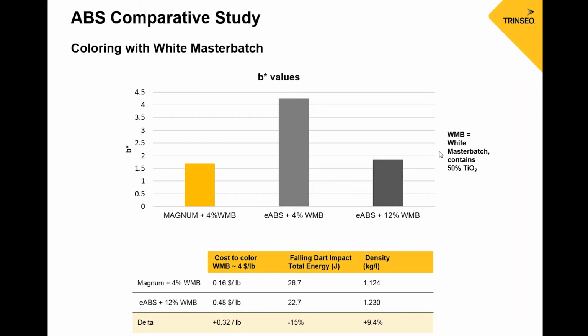So we compared using a 4% white master batch that contains 50% TiO2, using the same amount of that master batch with the Magnum ABS versus the emulsion ABS. You can still see a large difference in the B star value, even with that much TiO2 in the product. So we wanted to get the same yellowness level and see how much it would take, and it took 3 times as much of the white master batch to get to around the same level. So 12% versus using 4%, which can lead to cost reduction.